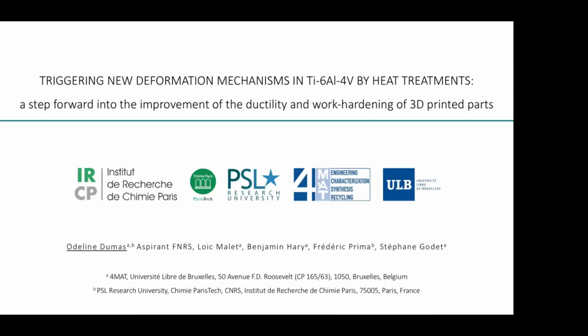Okay, I have another question on the chat from Charlotte, congratulating you on your work, and asking about the range of temperatures for your heat treatment which would allow you to see these reorientations. Okay, that's a good one. From 800 to 920 degrees, we could see reorientation, but above that, the reorientation is gone. We don't know at this stage if it's linked to the chemistry or the size of the martensite. We think it's both. It's more a problem of chemistry, because we could find some other alloys that have very big martensite laths and can induce reorientation without any problems. So we think it's more a question of chemistry.